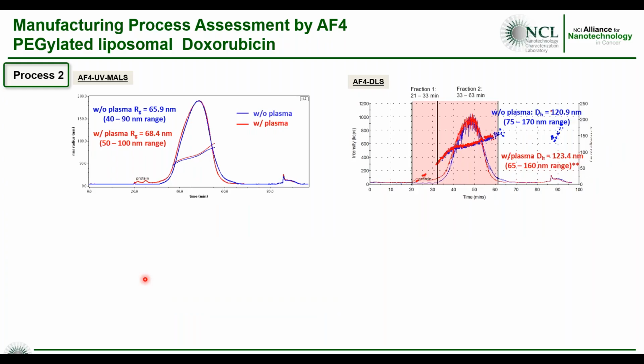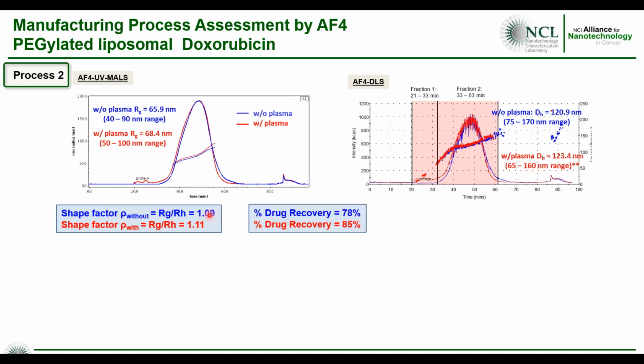If we look at process 2 and subject it to the same type of analysis, AF4 with MALS and AF4 DLS, we see that the shape factor actually increases. We get higher drug recovery for this sample, but the same free drug and same lipid amount in the formulation. But looking at the cryo-TEM, it's interesting because the size is larger now, still spherical with an aspect ratio of 1, but now with the drug crystal shape, we're seeing almost an even mix of linear versus circular. So we have the linear here and a circular drug shape morphology.